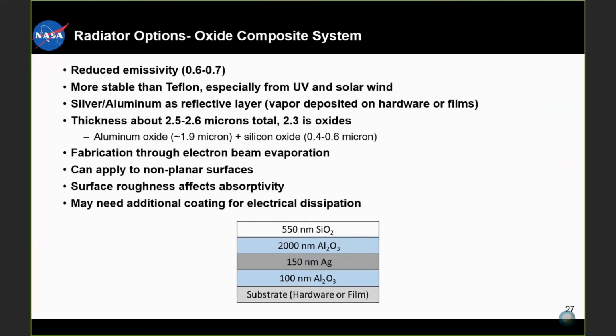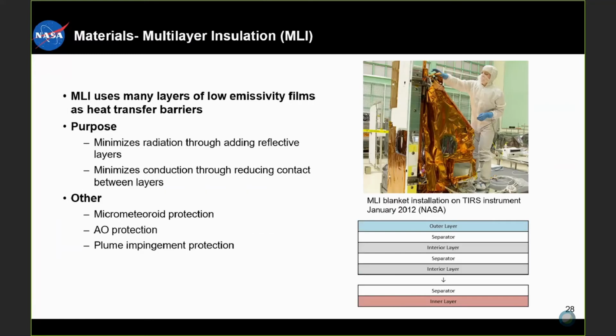The next material option for radiators is an oxide composite system. This will have a lower emissivity as compared to OSRs and white paints, at about 0.6 to 0.7. It is more stable than Teflon though, especially from UV and solar wind. It does use silver and aluminum as a reflective layer, which is vapor deposited on the hardware or films. Its thickness runs about 2.5 to 2.6 microns total, 2.3 of those are oxides, and it is fabricated through electron beam evaporation. This material option can be applied to non-planar surfaces, although eventually its surface roughness will affect its absorptivity. And again, it may need an additional coating to meet an electrical dissipation requirement.